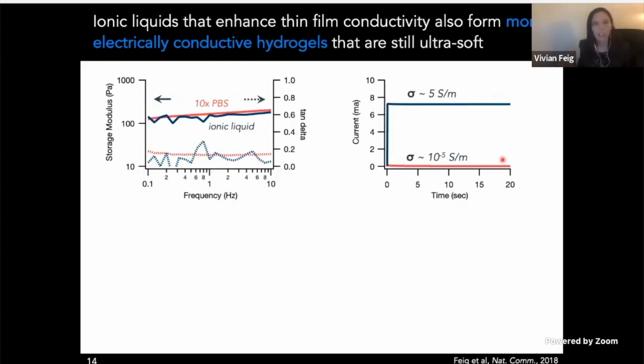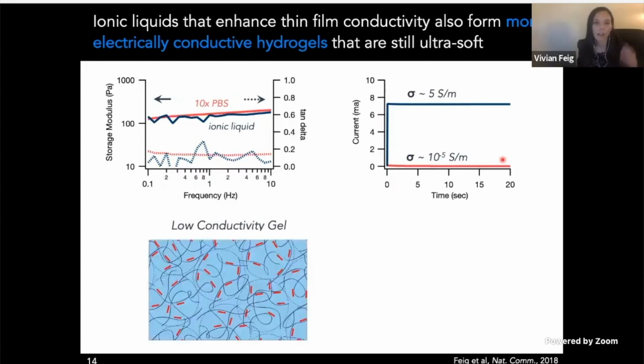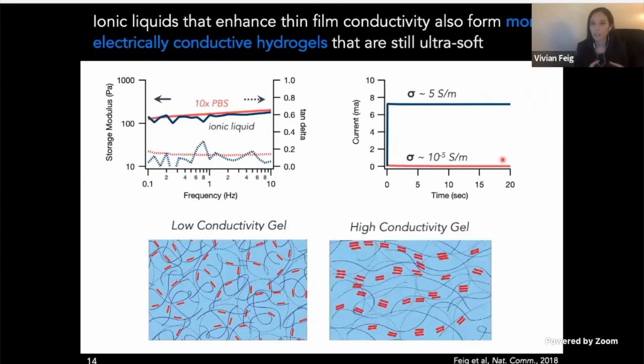And so with that, we propose that there's 2 types of conductive gels that we can form, where in the first case, where you're just screening those electrostatic repulsions and getting microgel aggregation, you're not actually changing the internal structure of those gels, and you end up with something that has very poor electrical conductivity. Whereas if you use these additives that can undergo counter-ion exchange with PEDOT and PSS, then you can form these much more electrically conductive gels, which we think probably has a similar type of internal structure as the thin films. And we still maintain these ultra-low elastic modulus values because of the high water content.